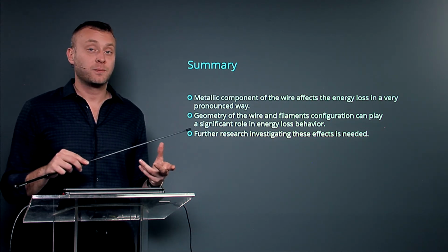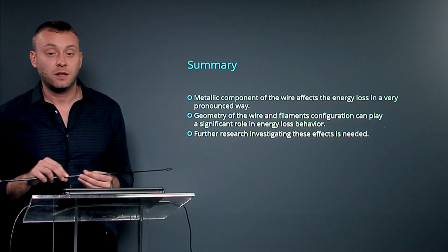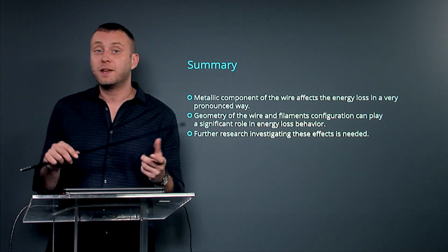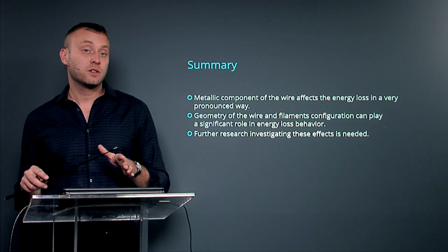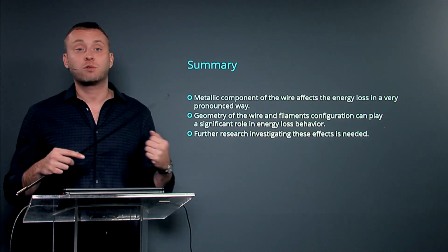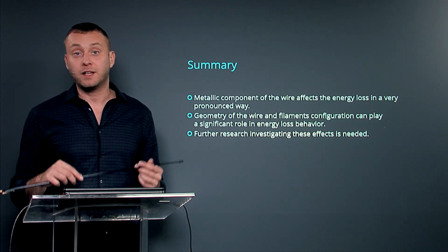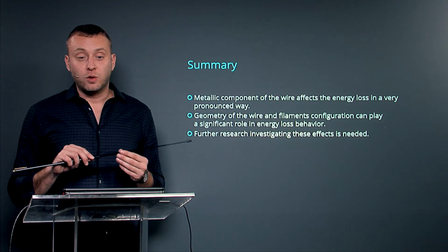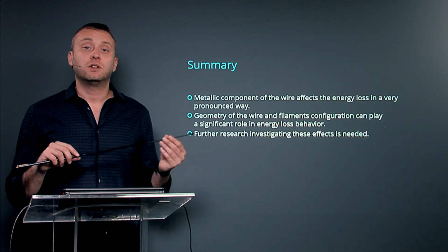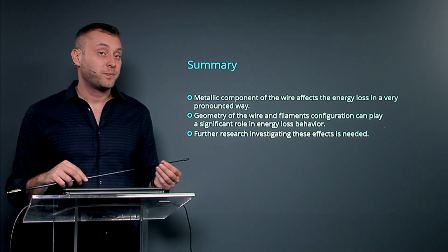And what we measure using this method, the electrical method, is the overall energy losses of the wire. We cannot distinguish what part comes from the superconducting losses and what part is due to interaction with the metallic materials. So we have to redesign our experiment.